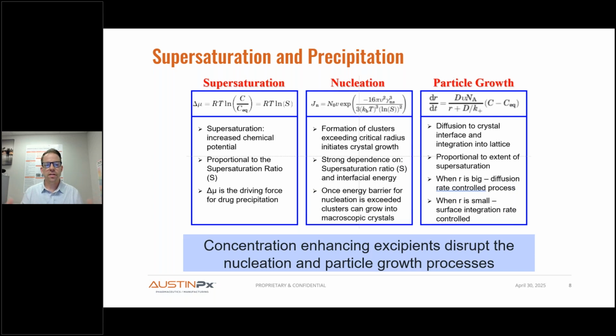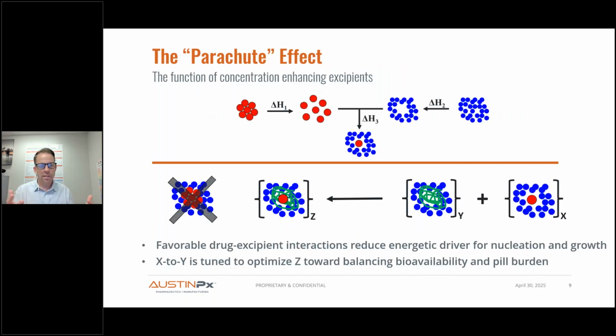Well, there are equations that govern supersaturation, nucleation, and particle growth. I won't belabor this to any great extent, but just know that it's foundationally understood. We know how formulation factors impact supersaturation, and then how they can impact nucleation and particle growth. The take-home message is that concentration-enhancing excipients disrupt the nucleation and particle growth process. They enhance supersaturation, and they disrupt the processes that accelerate nucleation and particle growth. And so we'll illustrate this by going back to that figure and pictorially describe this parachute effect and the function of concentration enhancing excipients.